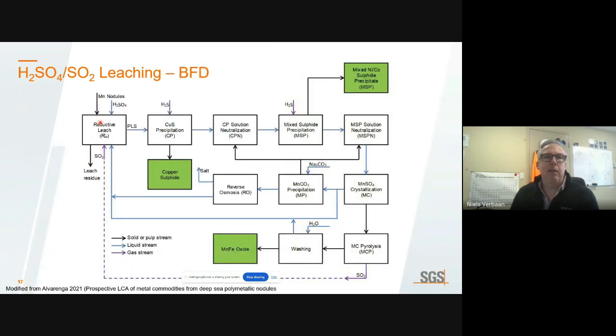So here's this flow sheet. Here's the leaching step. Copper sulfide is produced using H2S gas. A mixed sulfide precipitate, MSP as we call it, is produced using hydrogen sulfide gas. And here are the two innovative steps. Manganese sulfate is crystallized at temperature. This is not an evaporative crystallization step. This is heating it up. And these crystals are then pyrolyzed into SO2 gas for recycling and the production of a crude manganese iron oxide.